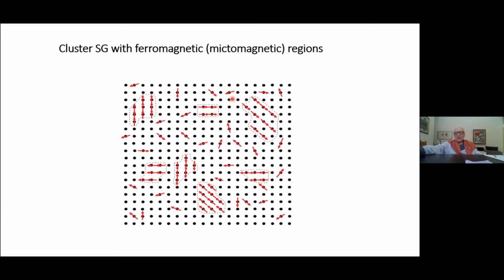I have some spins. This is so simple. I have some spins in a gold matrix. Gold is non-magnetic. These are iron spins. And I look at the interactions. I neglect these ferromagnetic big clusters, which come into later theories. However, this spin here is a first nearest neighbor, and it's antiferromagnetically coupled. If I come down here or come down here, this nearest neighbor spin is ferromagnetically coupled.